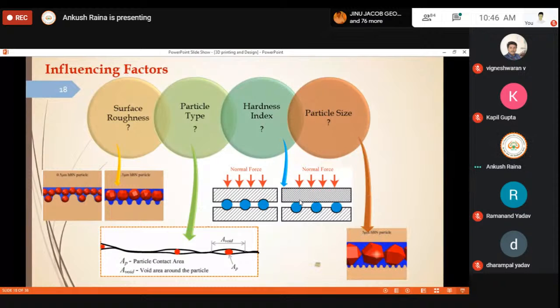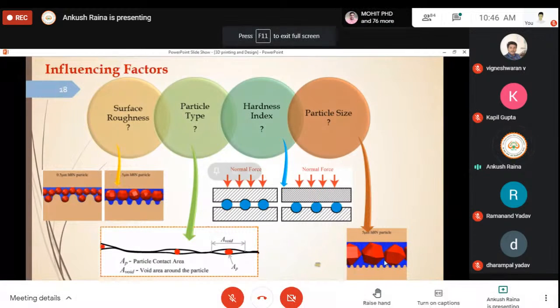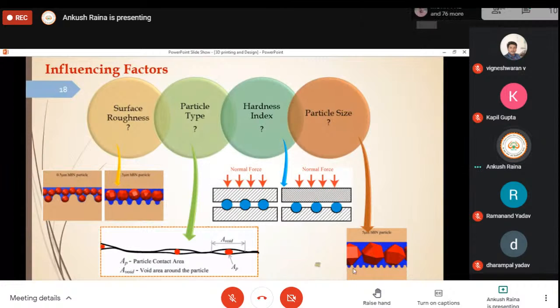Then comes the particle size. Obviously, particle size and surface roughness have a correlation. If there is more surface roughness, it means larger particles can be accommodated. If there is less surface roughness, the particle size should be smaller. Here you can see that the size of the nanoparticles is large, whereas the surface is much smoother. So these nanoparticles will not embed in these valleys. They will remain on the peaks, and certainly they will try to damage those peaks.